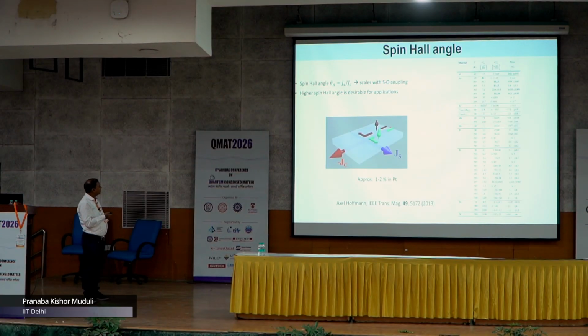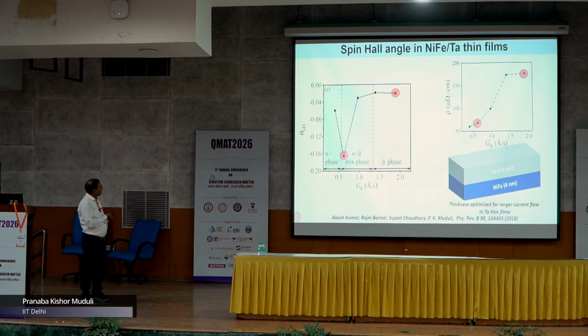But if you look at some literature, and this is now for certain heavy metals where this spin Hall effect is normally observed, such as platinum, which is the most common one, it is only 1 to 2%. Although this is a little bit old literature, and people have observed higher values in different ways, the value still remains lower. So this is one limitation for memory application, and there is a way to increase this.